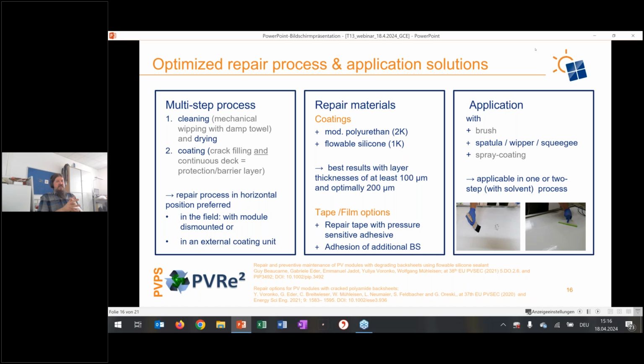How did we then do the repair? Overall, this is the outcome of the project. And if you're interested in the whole procedure, we did 2 publications on that that are open access, so you can look them up at the respective journals. So first, we cleaned the surface with just a damp towel, and then waited for a few minutes in order to have a dry surface. Then we did the coating.